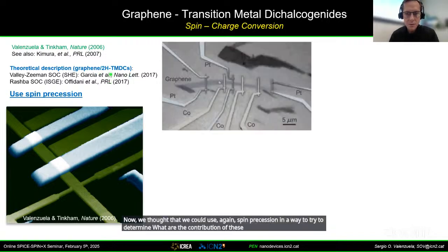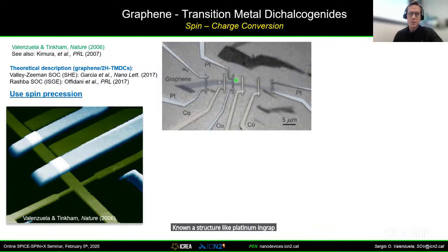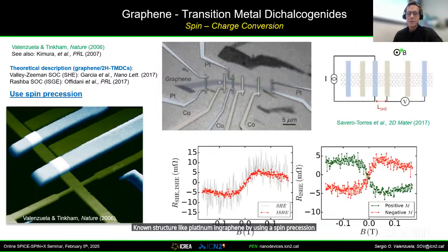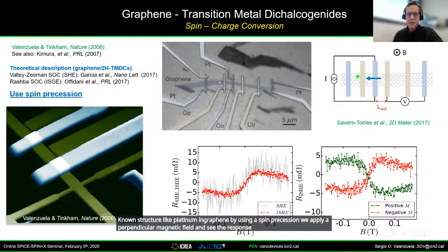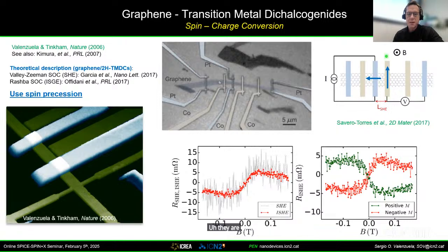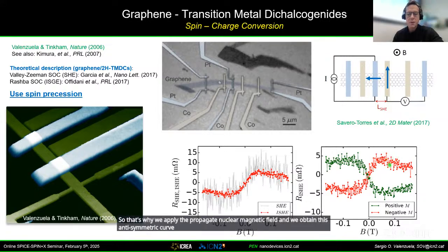And for that, we wanted to first study a system in which we can demonstrate spin Hall effect in a known structure like platinum on graphene by using spin precession. We apply a perpendicular magnetic field and see the response. And you can see that for a spin Hall effect to be detected, it has to be in this direction. The spins are generated in this way, but the spin polarization of the electrons is in this way. So you have to make this a spin precess. So that's why we apply the perpendicular magnetic field, and we obtain this antisymmetric curve. These days, people describe this as antisymmetric Hanle.